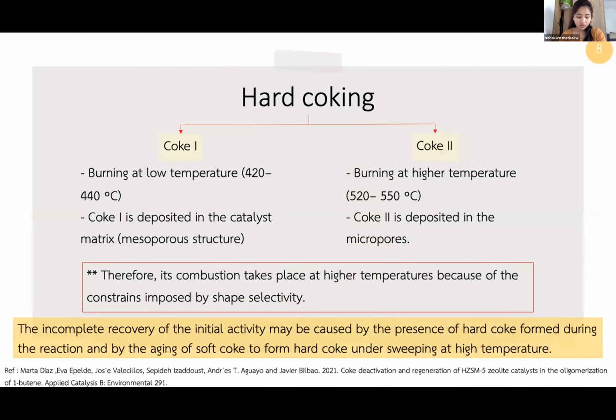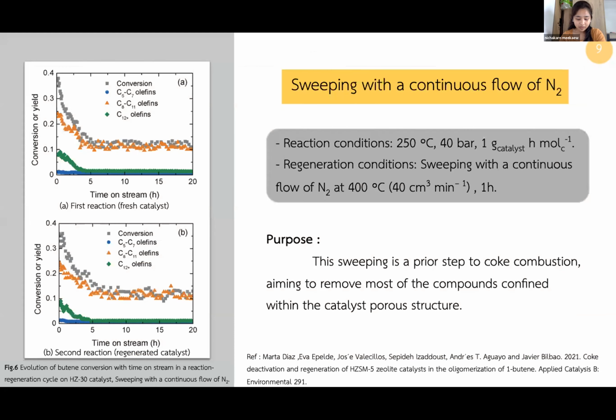There are two fractions of hard coke, the first one burning at low temperature and the second burning at higher temperature. Its combustion takes place at higher temperature because of constraints imposed by shape selectivity. Thus, hard coke that remains after sweeping will require a subsequent combustion step for its complete removal.